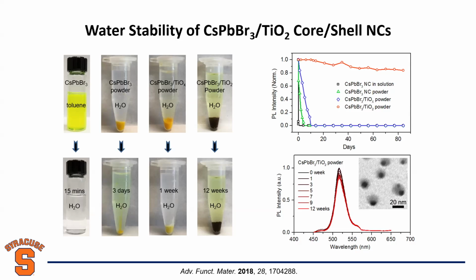But when we look at the TEM image, you might notice sometimes TiO2 wraps one perovskite particle inside, sometimes wraps two, sometimes wraps three. And you look here, the shell is not symmetric or uniform in thickness for the TiO2 shell, right? This side is thicker, this side is thinner. The reason is this is not epitaxial growth of shell materials on a substrate. This is just like you wrap it, like wrapping a plastic bag on the surface. This is a very fast reaction. So you can see the shell thickness is not uniform. They are not monodispersed core-shell particles.